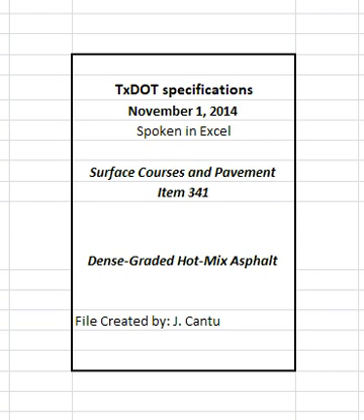Use RAS from shingle sources on the department's MPL. Remove substantially all materials before use that are not part of the shingle, such as wood, paper, metal, plastic, and felt paper. Determine the deleterious content of RAS material for mixture design purposes in accordance with Tex-217-F, Part III. Do not use RAS if deleterious materials are more than 0.5% of the stockpiled RAS unless otherwise approved. Submit a sample for approval before submitting the mixture design. The department will perform the testing for deleterious material of RAS to determine specification compliance.